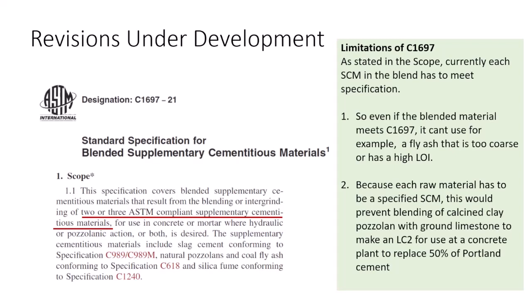And that was the one I mentioned before, about each one of the raw materials in that spec having to be ASTM compliant on its own, and that causes some restrictions on evaluating materials that could be used. And that would also be an issue if you're trying to make a blended limestone clay system, like what I would call an LC2, to replace 50% of your clinker with a blend of limestone and clay. Right now, that would not be allowed under this spec because limestone isn't defined as a supplementary cementitious material. And that is an impediment.